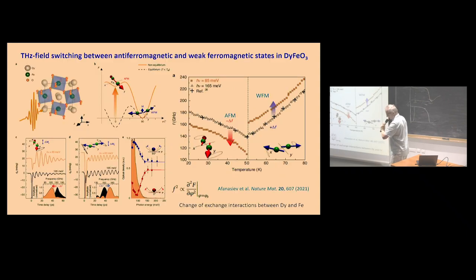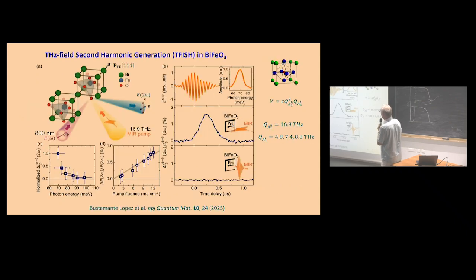I do not have too much time because I would like to speak also about other things, but in dysprosium ferrite a change of magnetic structure was also observed. Here is a spin reorientation phase transition from weak ferromagnet to antiferromagnetic phase. And when they pumped the phonon, again, there was a possibility to change the antiferromagnetic resonance, shifting it down or up, and the ferromagnetic resonance. But I will skip this.